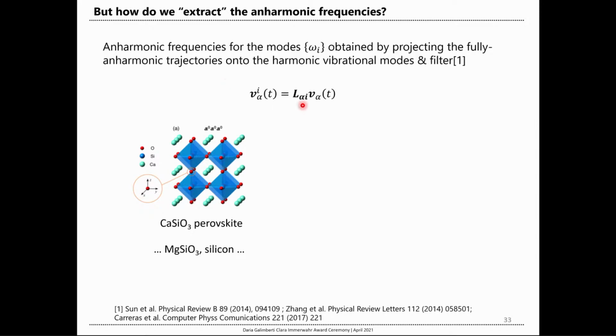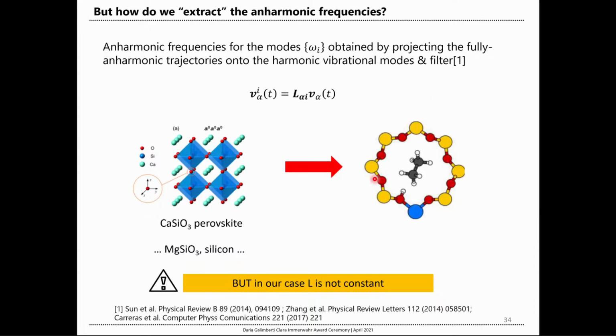But there is a small problem. Even if you look at this equation, this L matrix, the matrix that describes the normal modes, does not depend on time. So it's a fixed quantity. And so we have an underlying assumption that the normal modes are not evolving during our molecular dynamics simulations. That is true in the systems that they were studying. But if you think about what we want to do, that is, this kind of system in which you have a framework that is vibrating with large amplitude motion.